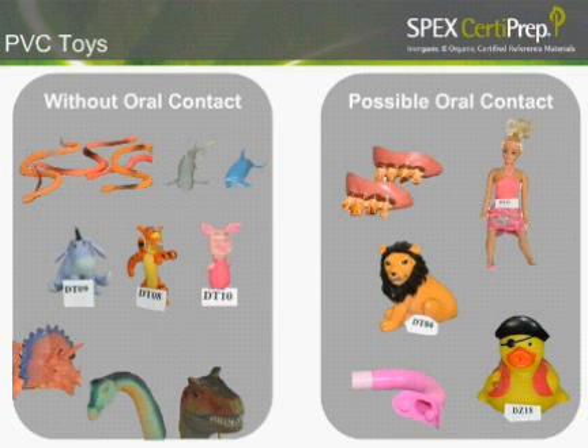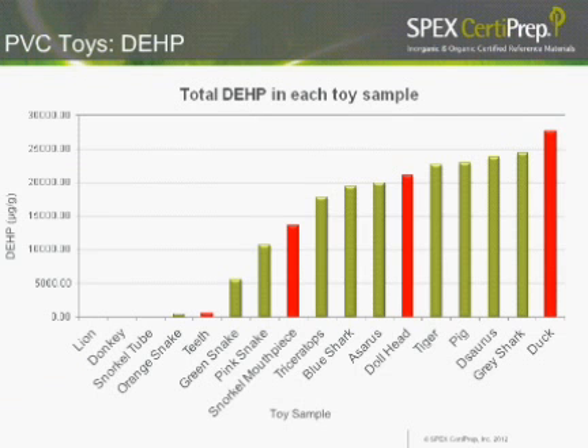For our PVC toys, we had a lot broader range of results. For our toys without oral contact or possible oral contact, we found a whole host of different phthalates, but the most prevalent phthalate in all of our toys was the DEHP. You can see here of all of our PVC samples, starting with our lion and going through with our friend the rubber duck, and the level of DEHP, if you compare it to what's allowed by the Consumer Product Safety Commission at 1,000 micrograms per gram, almost all of our toys exceed that level.